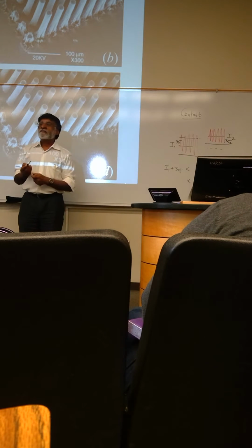Therefore the contrast H that you will get, in order for it to be meaningful, should be greater than this divided by I1. That is the condition that you need in order to have a good technique.